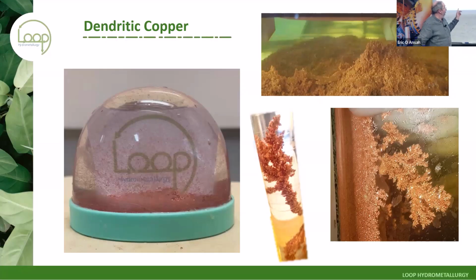By the way, I grew these dendrites long just to show what an ugly dendrite looks like. So what we've done in the Halion cell is we have deliberately changed the way that we operate the cell to continuously remove a small rain of small particles off the cell. And it's all based on the fact that we figured out how to control the growth of dendrite on a cathode. And then once you figured out how to do that, you can then design your whole cell around an easily operated cathode.